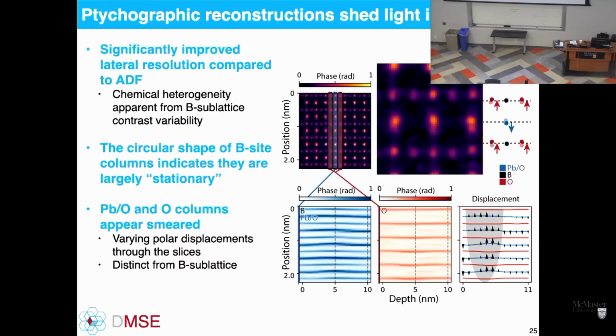And what I'll see here is that as I go down that lead-oxygen column, at a certain point the lead-oxygen column actually flips at 2 different positions, right? And with oxygen staying in the same position, the B sublattice, that is magnesium, niobium, or titanium, all stay locked to the same position. It's the lead that's responding to the local chemistry, and we're essentially seeing a 180-degree domain rotation of the polarization through the depth of the sample. This was sort of unthinkable in terms of what you could do from one single data set acquisition on the microscope previously.